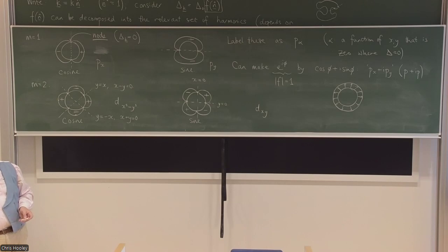The simplest example for the high TCs is that it's forming superconductivity out of a repulsive interaction. And you can't form S wave superconductivity out of a repulsive interaction, but you can form some of these other channels out of a repulsive interaction because you can effectively flip the sign of the pairing interaction by flipping the phase of the superconducting order parameter. So something which has a plus lobe talking to a minus lobe can pair even if the interaction is repulsive.